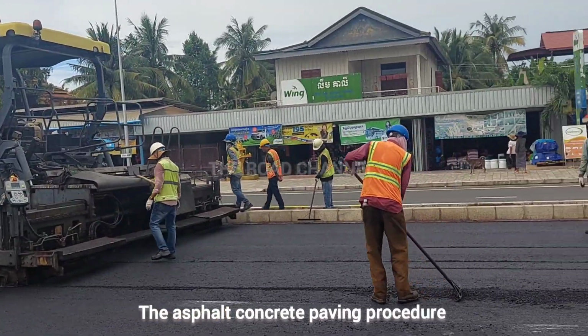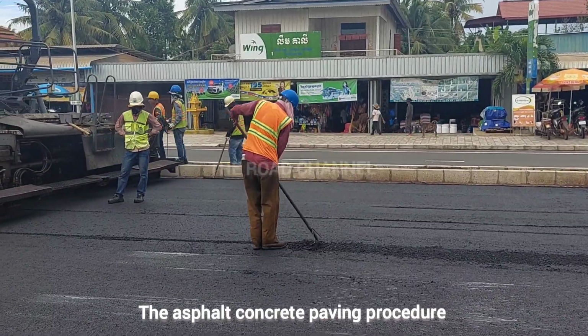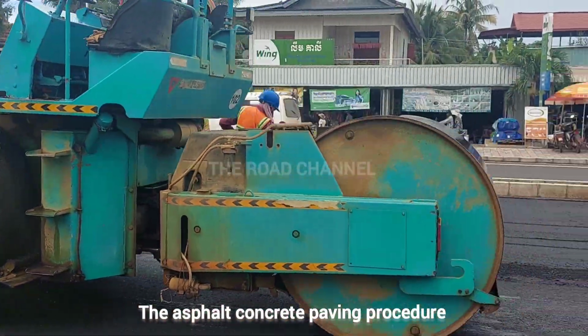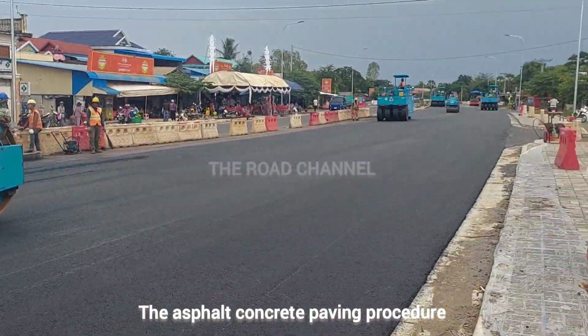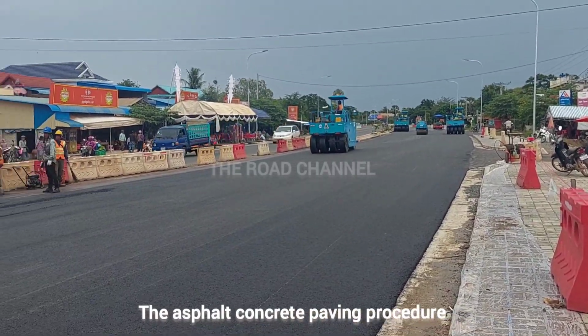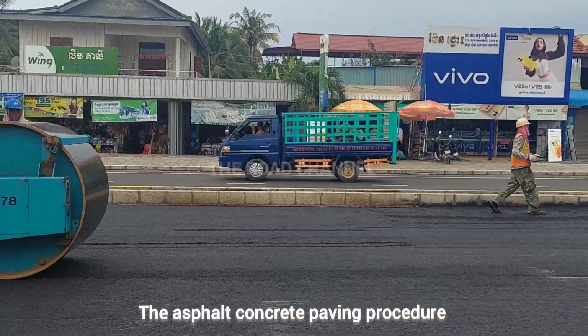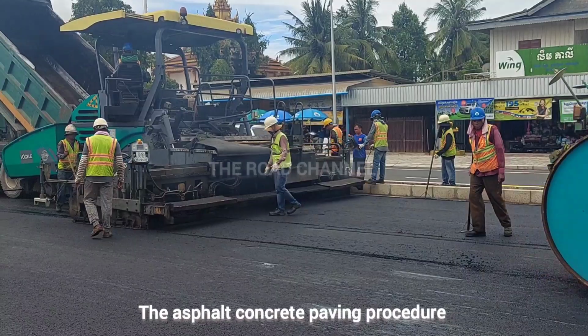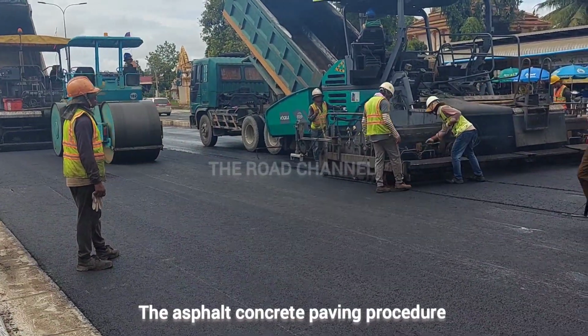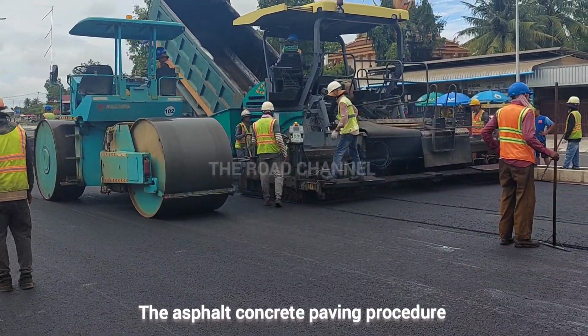4. Compaction. Initial rolling. Use a steel wheel roller in the breakdown phase to achieve primary compaction. Intermediate rolling. Apply a pneumatic tire roller to further compact and seal voids. Final rolling. Use a finish roller to smooth the surface and achieve the required density.